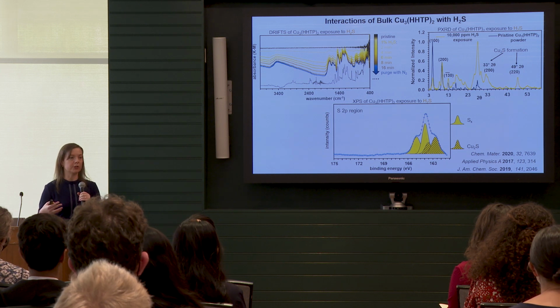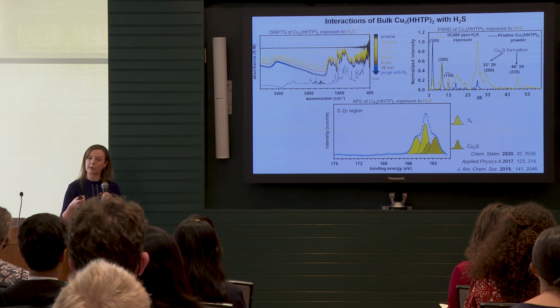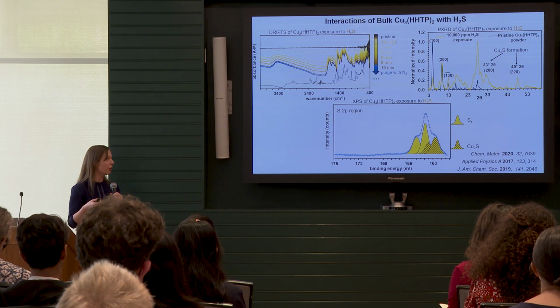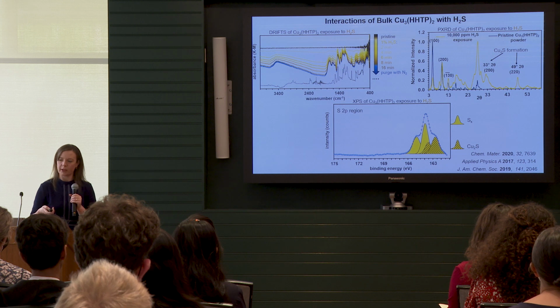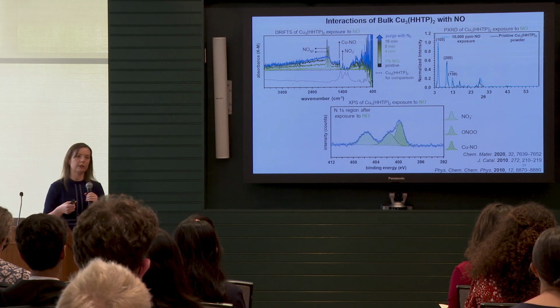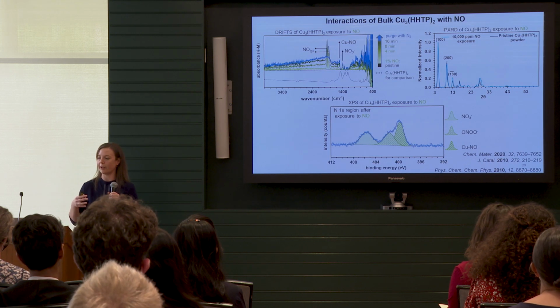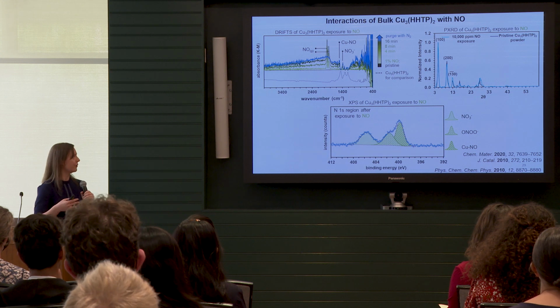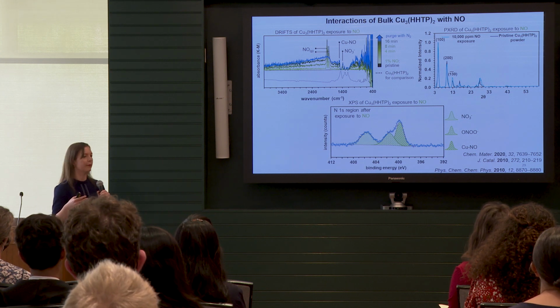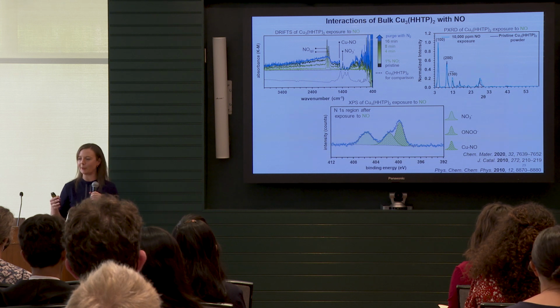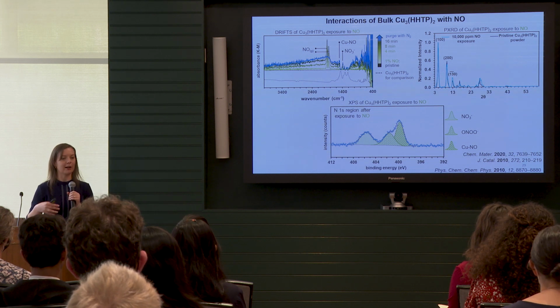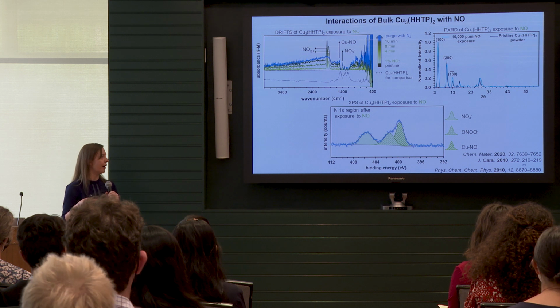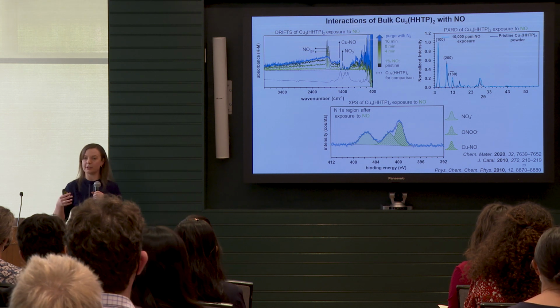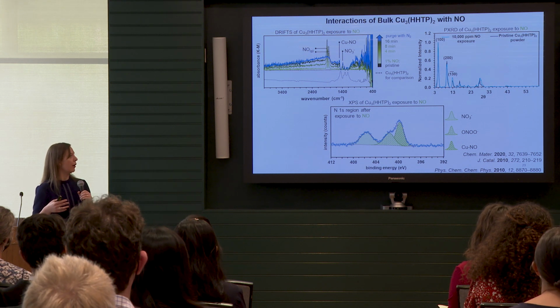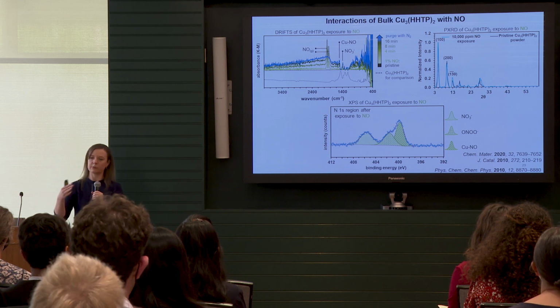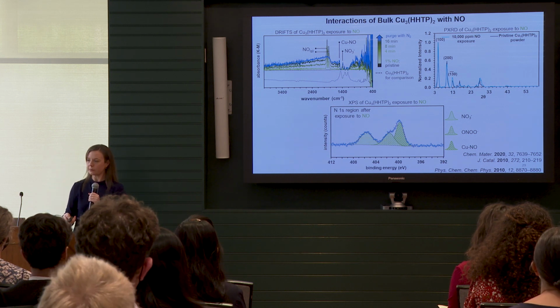So in the case of hydrogen sulfide, we're actually trapping it within the framework as sulfur 0 or copper sulfide species. In the case of nitric oxide, and we determine this by a combination of X-ray crystallography, X-ray photoelectron spectroscopy, and diffuse reflectance IR spectroscopy, we're actually oxidizing it to nitrate and other similar compounds, nitrite. We also get direct binding of the nitric oxide to the copper metal.